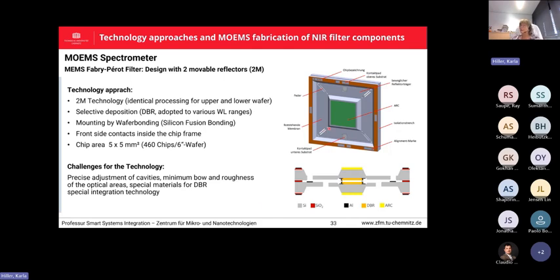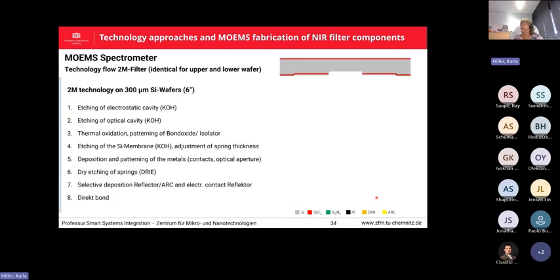So this slide we have already seen. And I also explained already what it's good for to have these two movable reflector carriers. And now again, I want to show some details about the technology, which is now identical for the two wafers. So again, we start with creating the cavities, defining later on the optical and the electrostatic cavities. Then we deposit a thermal oxide, which has influence on the distance between the two layers, but is also at the same time our bonding material.